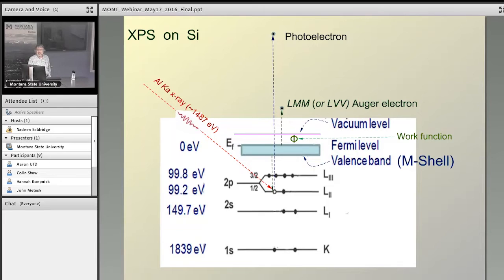The first electron, where the hole is created, is called the L level, so it starts with L. The next electron that fills it is from the M levels, M, and another electron goes out, it's the M electron, so it's LMM. And the electrons that are lost in this valence band are filled back essentially through the ground. Essentially, the system is neutralized immediately within 10 to the minus 9 seconds. That's how efficient it is, otherwise your spectrum will not work. So that's Auger, that's X-ray.